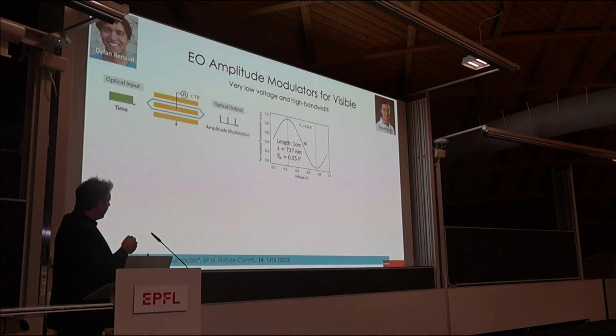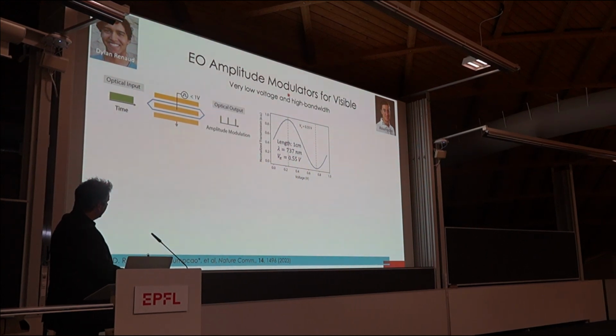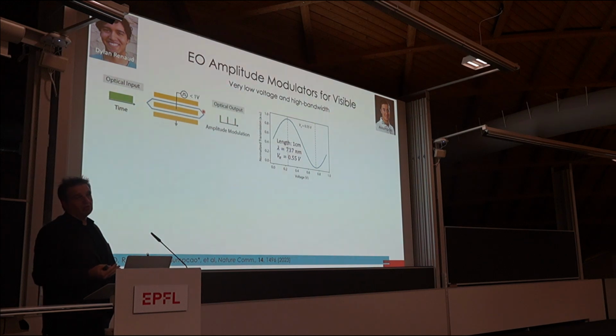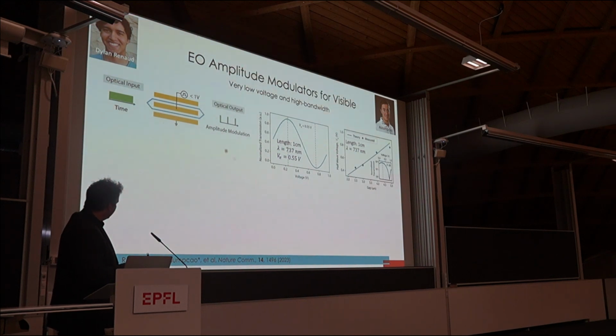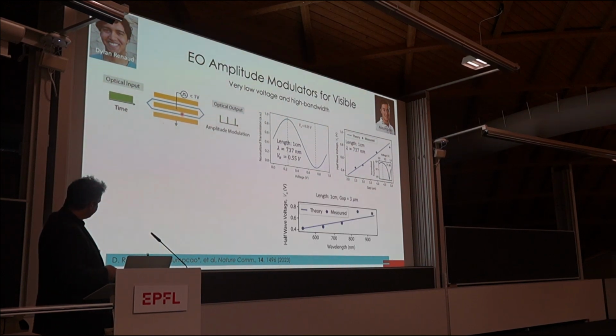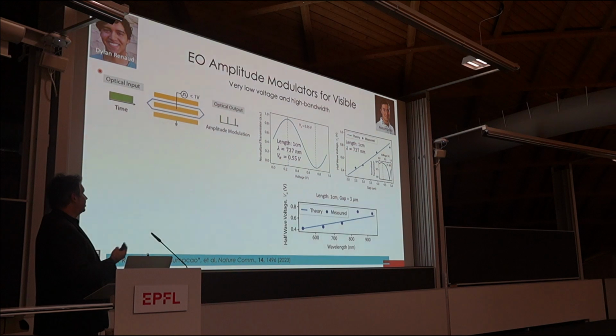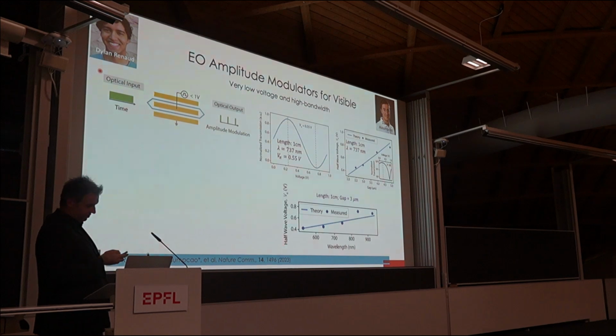Our modulators in visible have so-called V-pi voltage, which is the voltage required to get the 2 arms of this Mach-Zehnder out of phase, right? It's about 0.5, it's half a volt. We can actually go much less than that also if you trade off for some loss. And then if we go to shorter and shorter wavelengths, actually this is the trade-off. You can go even around 0.4 volts if you allow for a little more loss in the interferometer. And also by going to shorter wavelength, you can further reduce this. And since this was submitted on arXiv, we and others have also done much better. The bottom line is, I think 0.1, 0.2 volts is not out of the question for some of these devices in the visible wavelength range.